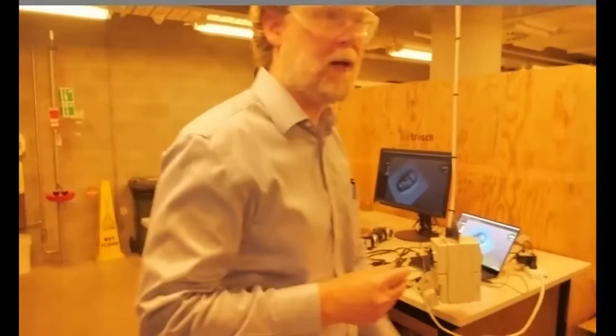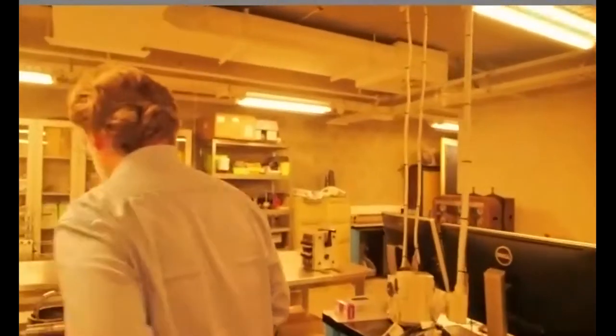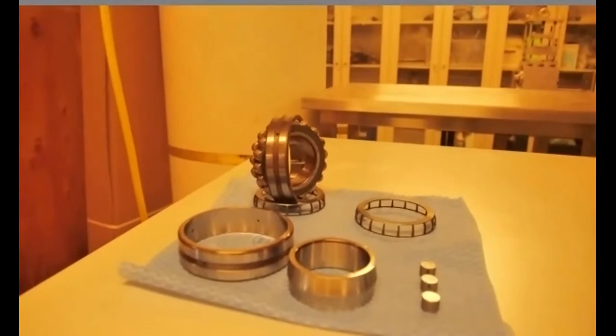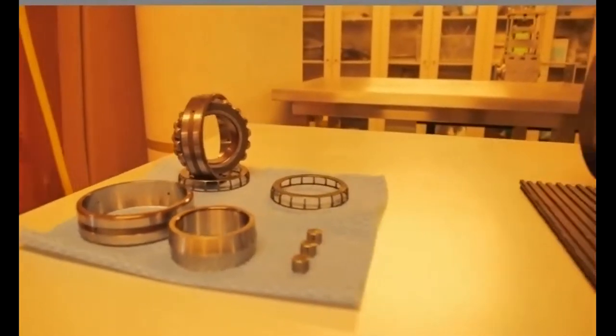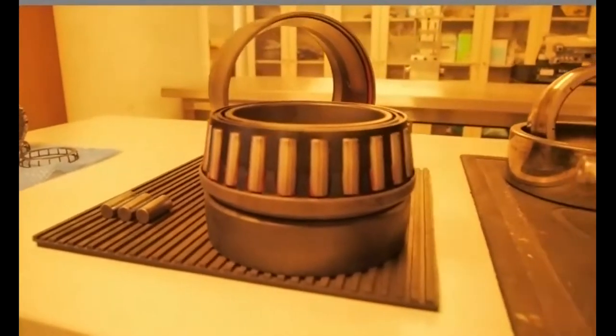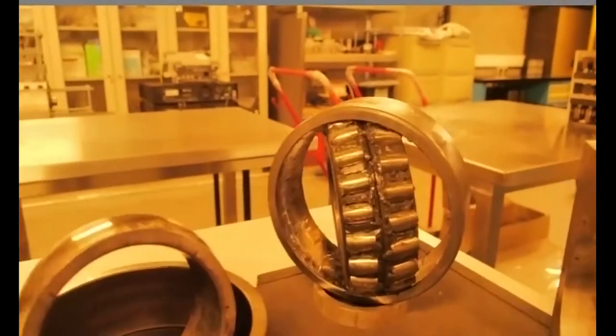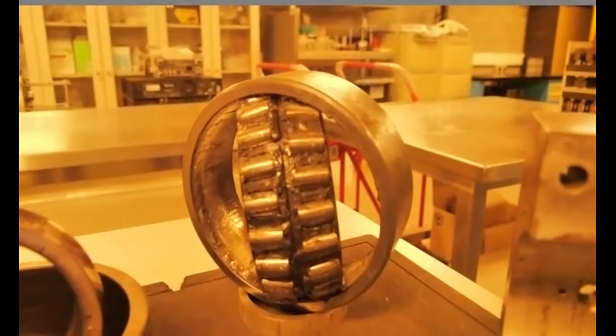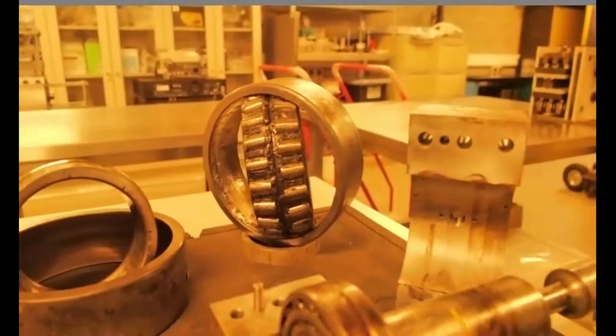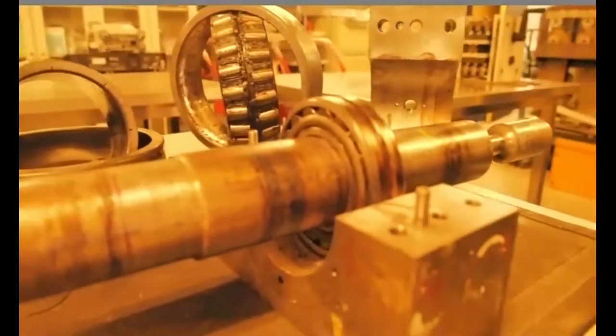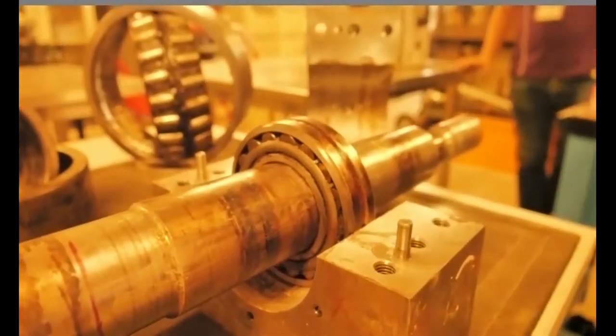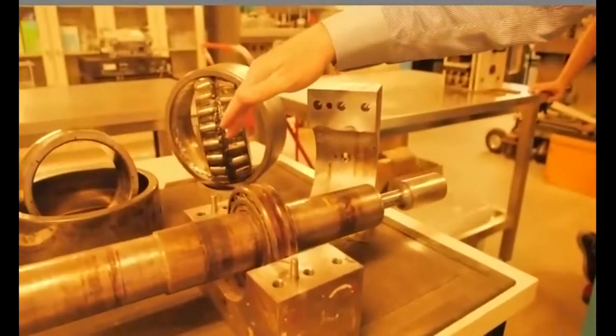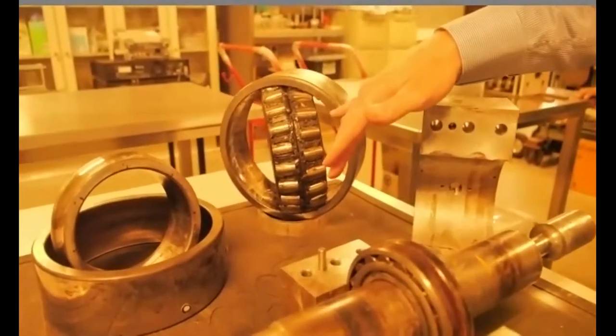Okay. Thanks, Xing. I'll take you over to a number of bearings. So we've recently completed and are doing a number of projects related to bearing wear and tribology. What you see here, see this large bearing here and another one here, which is a spherical roller bearing. They're the large bearings used in railways, in particular the bogies. And there's many of them in a fleet of trains, and they're very costly to maintain. So every 8 years or so, you need to replace these bearings. And the main reason why we've realized is mainly due to the life of the grease, so the degradation of the grease you see there.